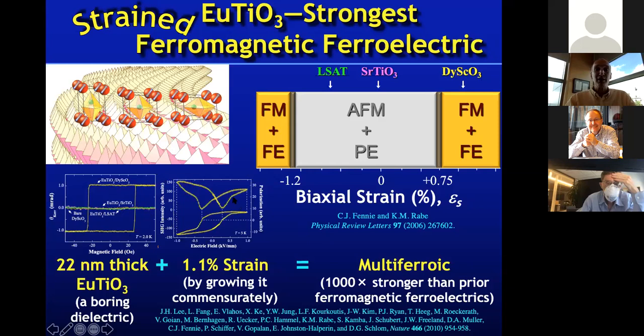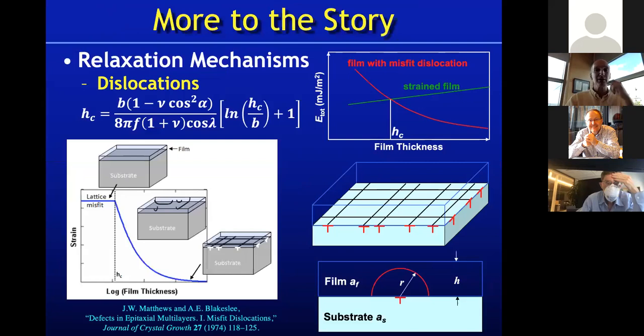Here we use second harmonic generation. And you can see from the second harmonic generation, reconstructing the hysteresis loop, that it's simultaneously ferroelectric and ferromagnetic, by putting it on top of a dysprosium scandate. So here I hope that I've emphasized the inner workings of what's going on inside of this material, for this relatively simple example of how you can change the ground state of a quantum material.